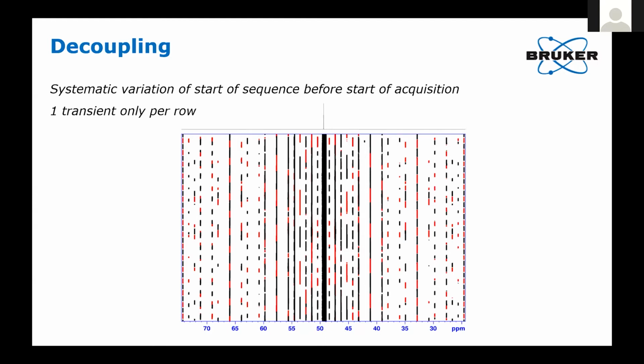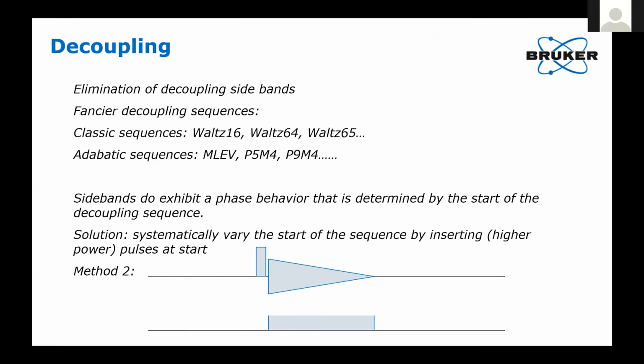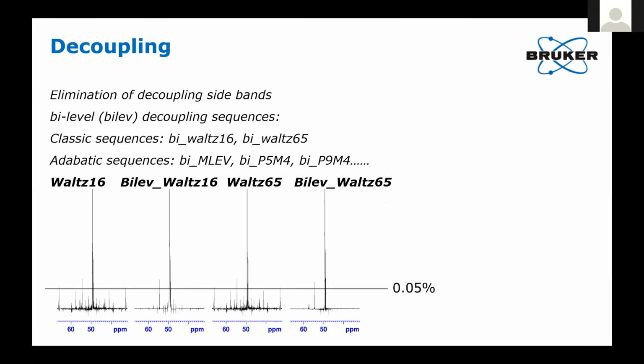The other possible approach is to shift the decoupling sequence to the right, but you can't have a gap. So what you do then is a series of typically higher power pulses to get a little bit of better behavior in there. With that, you can now reach excellent performance.